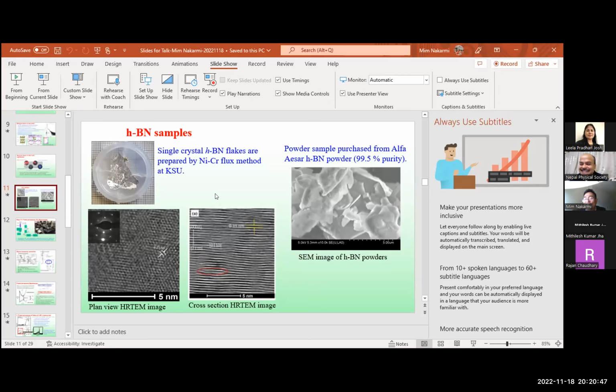That's why I asked you. The thickness should be very, very thin, in the nanometer range. So the way we do it is not that the whole material is 300 nanometer. The sample is stuck on the substrate, the substrate is holding it, and then the sample is cut in a slanted way by ion beam, and then at the edge it will be thin. Okay, great idea. Only that edge part is used to image in the TEM.